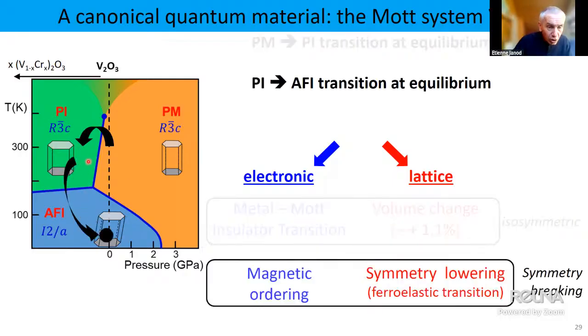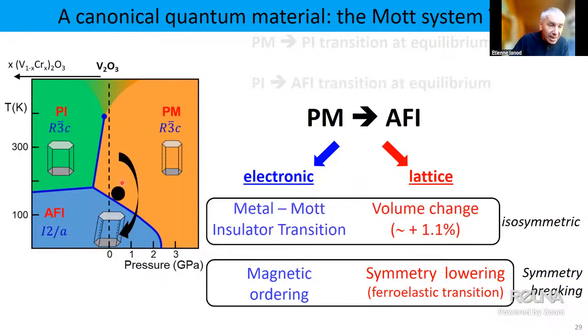And if we continue the trip in the phase diagram, if we cool down, we cross another line, which is the PI to AFI transition line. This line is purely symmetry breaking. That is, there is a first symmetry breaking, which is magnetic long-range ordering. And also there is symmetry lowering. You see, we go from a trigonal to a monoclinic space group, which we call a ferroelastic transition. And therefore, if we go from here to here by crossing these two lines, you will not be surprised that going to the same final place by crossing this line will be more complex and will gather the isosymmetric and the symmetry breaking transitions. So indeed, here we have metal-insulator and volume change, but also magnetic ordering and a ferroelastic transition.